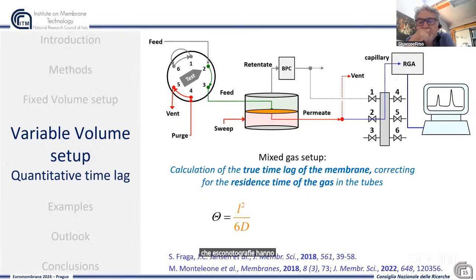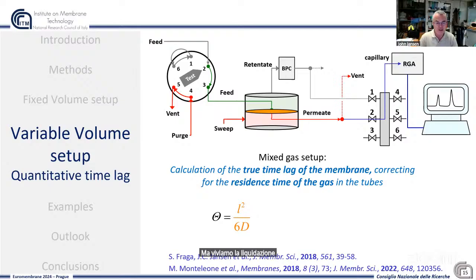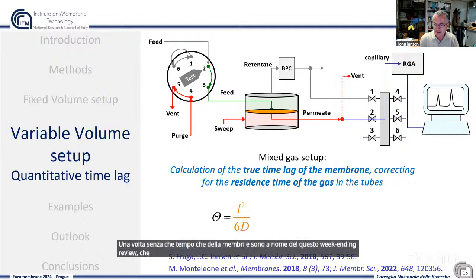The traditional method is using a GC, gas chromatography. Well, even the faster micro GCs are still slow. You need some tens of seconds to get a single measurement point. We would really like to see what's happening inside the membrane at every moment as soon as you expose it to the gas, or what happens if you change the temperature, or if you expose the membrane from a dry gas to a wet gas. You really want to see the reaction of the gas. And that's why we needed a faster gas analyzer.